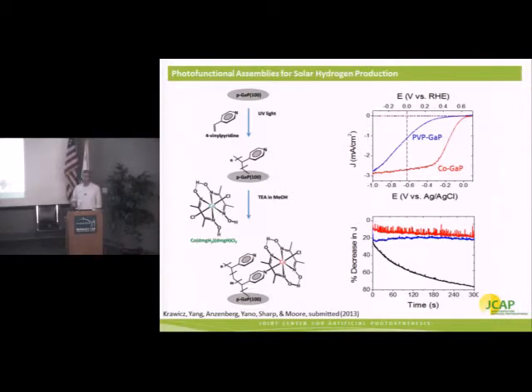So given a photoanode that we could couple to with sufficient voltage itself, we should be able to spontaneously split water with such a device. The activity is stable once we have the polyvinyl pyridine on the surface. So this shows a stability measurement over a course of just 5 minutes here, but we can already see dramatic differences.